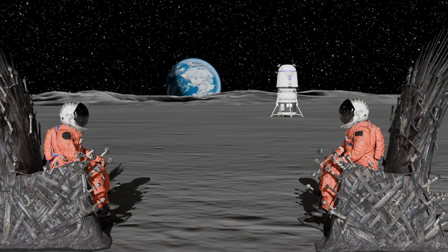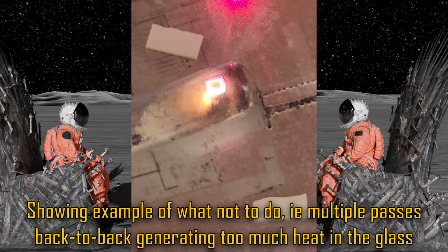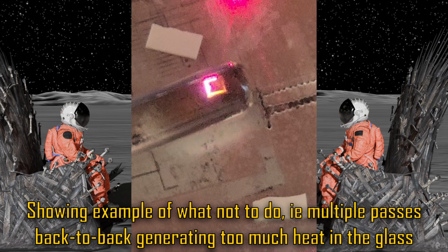But it did sort of become a problem because in order to see how pure the metals are, we needed to test how electrically conductive they were. And if everything's fusing with silica, it's going to increase its resistance by a lot. So it's going to make it harder to quantify how pure our deposits were. But you found out that just doing one pass of the laser at a time was enough, and then letting it cool, and then doing another pass.